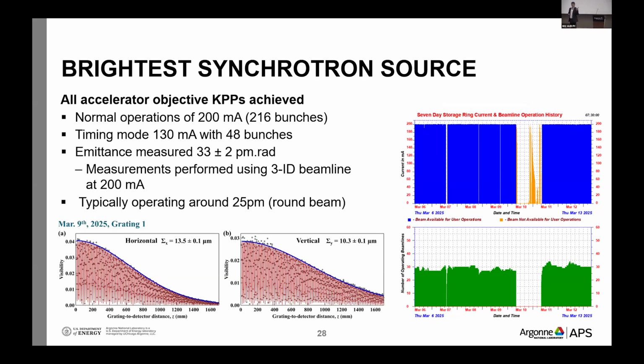So this is really much, much smaller, but also kind of symmetric, even though it's not perfectly symmetric because of the aspect ratio of the beam in the straight. So the measurements indicated an emittance of 33 picometers in both directions, so it's kind of a round beam. And typically, this was done with a single beamline operating for the measurement.